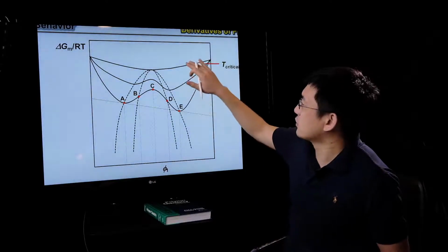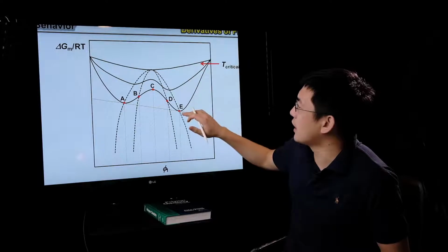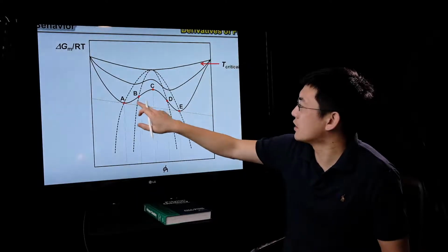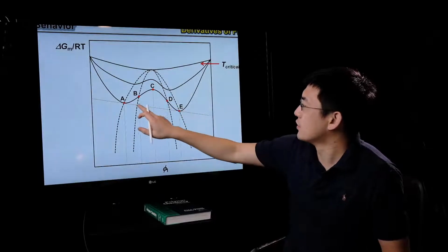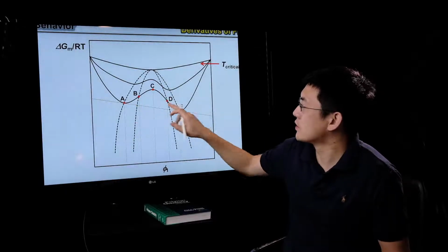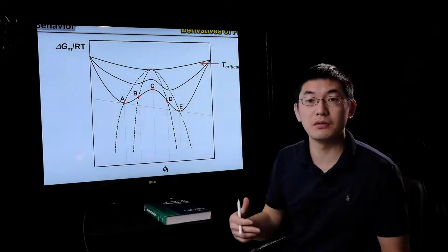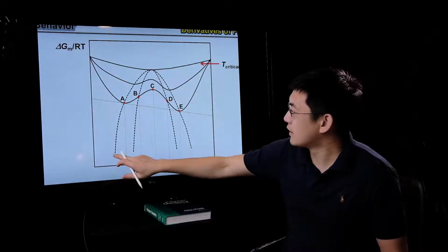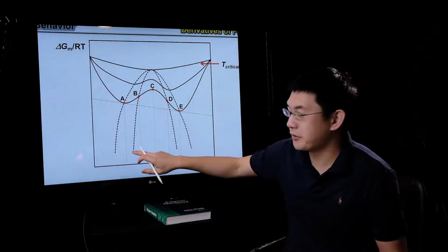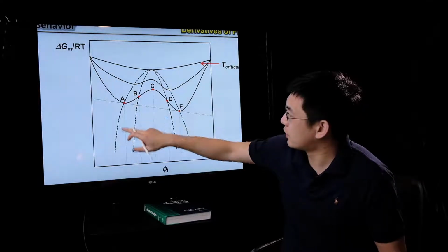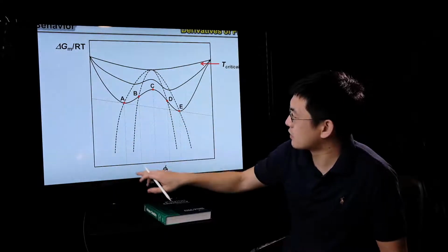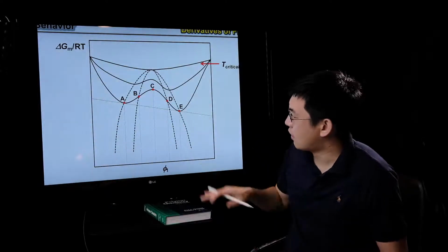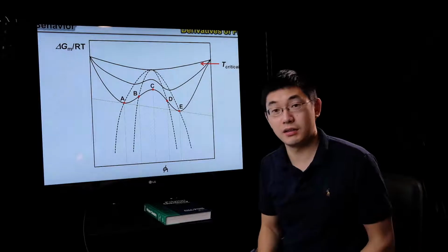So with respect to 3 different temperatures, now we have 3 different data points, and these 3 data points are going to be spinodal, binodal points. And every time we change the temperature, you would generate a new spinodal and binodal point. And this is why, if we do it repetitively, you can plot a phase diagram, which is plotted as temperature with respect to phi. Okay, so this is how we get it.